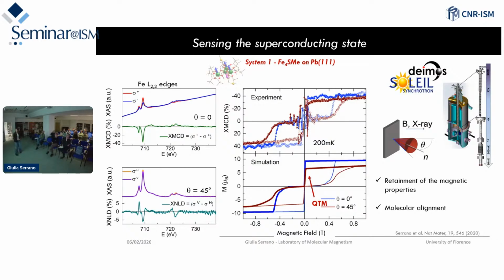And then we performed, as I mentioned, the XMCD spectroscopy. So we probed that we got the expected fingerprint from the XMCD signal from the iron magnetic core. We used also linear polarization to obtain this signal that tells us that actually we have a high ordering of the molecule on the surface. And most importantly, we went at the energy of the maximum, the minimum of the XMCD, and we scanned the magnetic field at 200 milliK. So this showed a very large hysteresis loop.